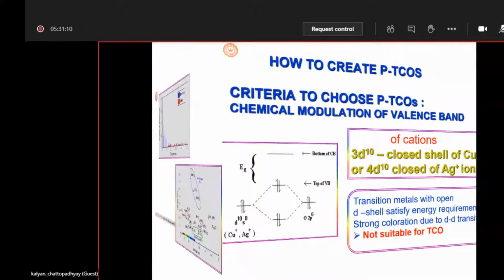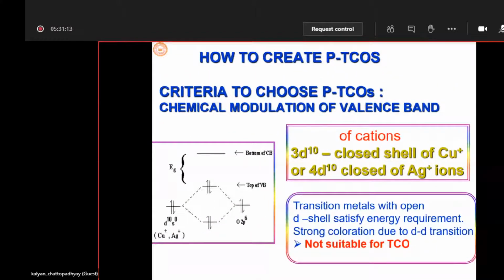The way out is that, as you have seen, the valence band is basically spatially confined from the oxygen p orbital. So we have to engineer the valence band. We have to disperse the valence band. How can we do that? This is a technique which is called the orbital alloying technique.